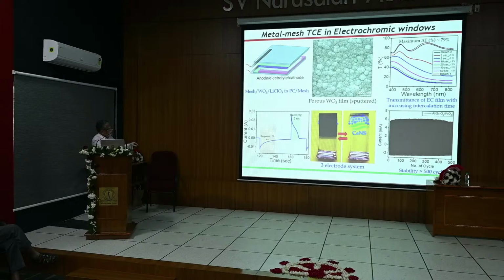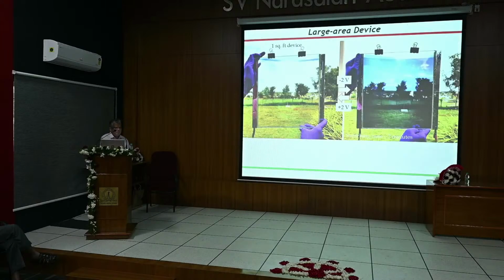A small piece of glass. These are charge-discharge cycles which correspond to the lithium intercalation and deintercalation. And they can stand lots of cycles, 500 cycles are shown. That talks about the stability aspect in that view graph. So these are like everyday stuff in the lab. We go on making them for various purposes. This is a slightly bigger piece of glass, and by application of -2 volt, +2 volt, we can switch the transparency aspect. It's totally transparent. This is colored transparency. Various color gradations we can try with these devices.